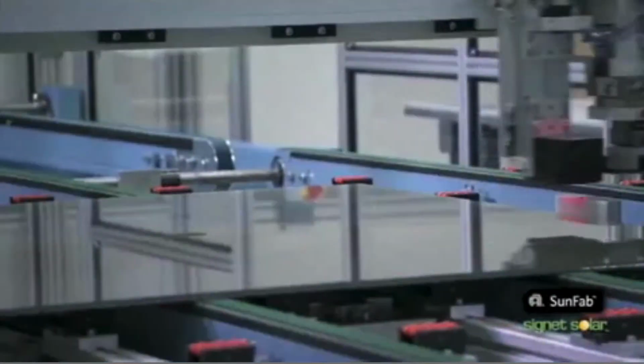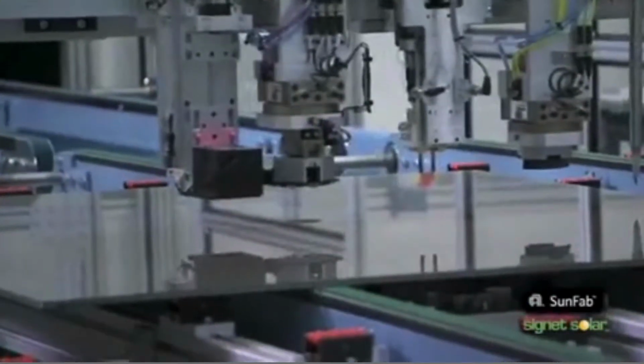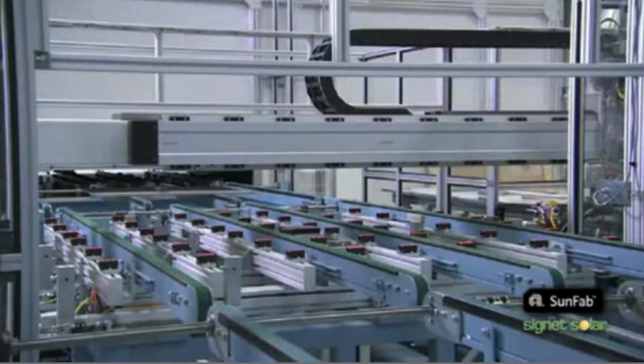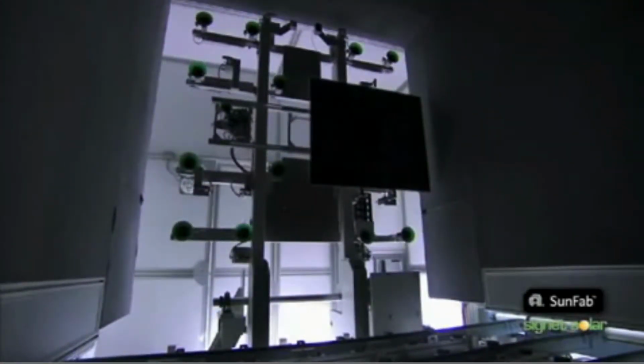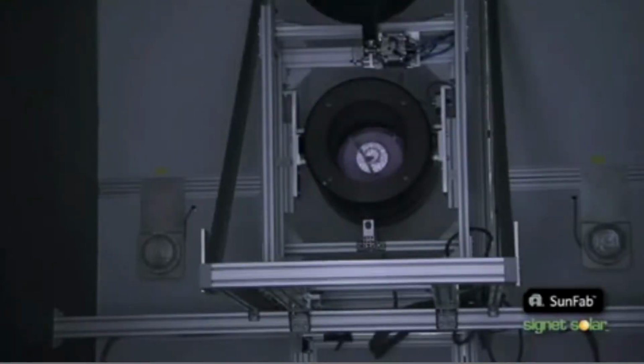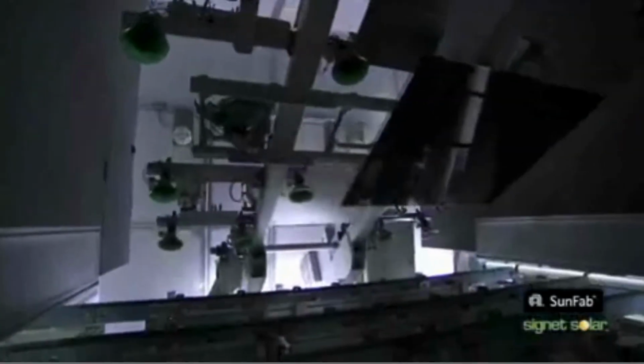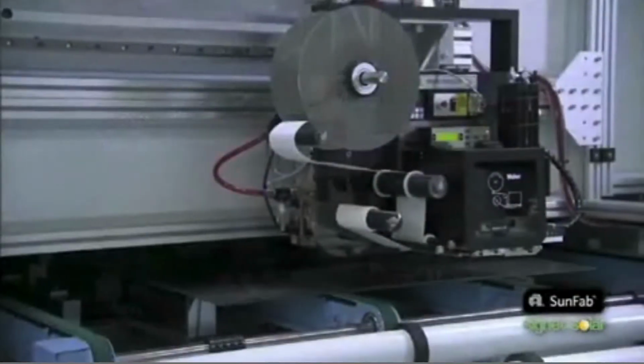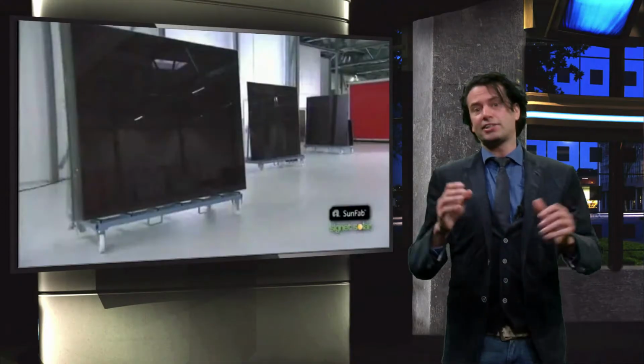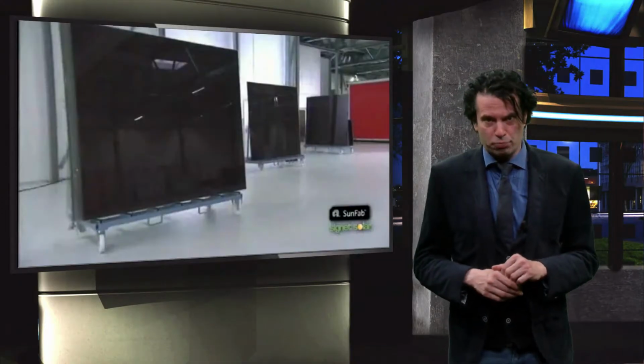Finally, a junction box is connected to the module with standardized connectors to facilitate installation. The performance of the module is then tested by a solar simulator to see if the module meets the specific output requirements. The yield of such a production line is generally over 95%, meaning that under 5% does not meet the specified requirements and is discarded. We now have a finished PV module. This is the most common thin film production process.